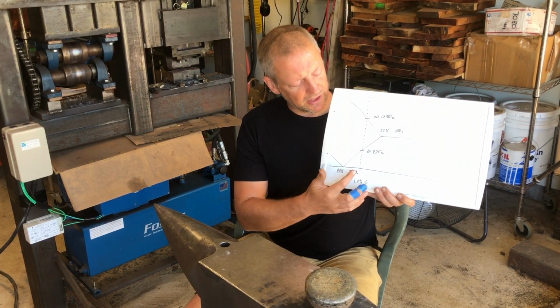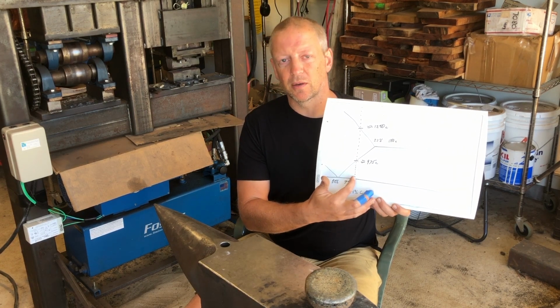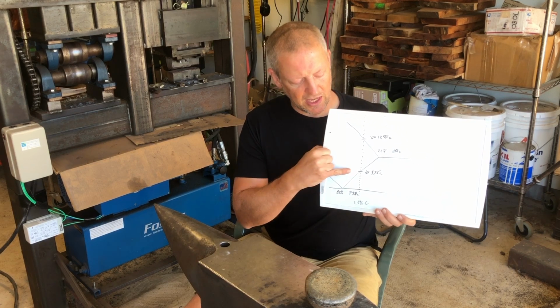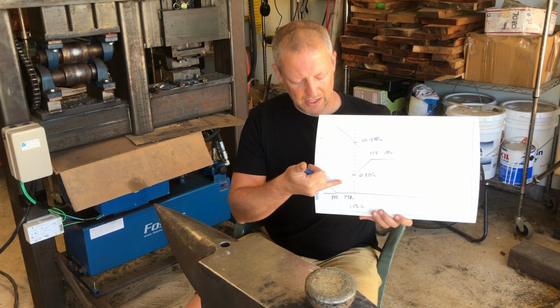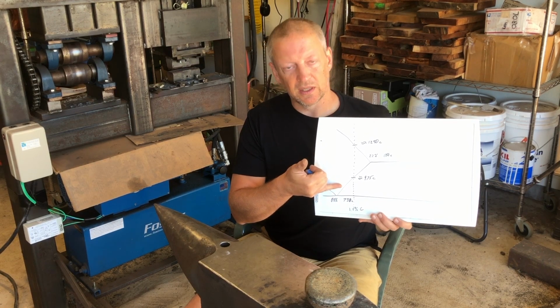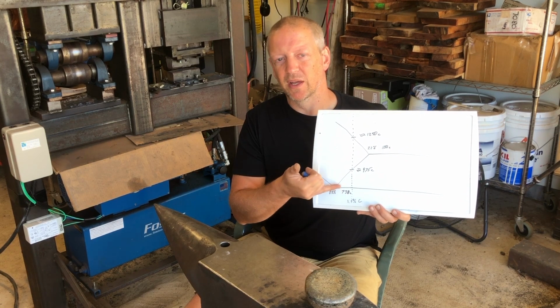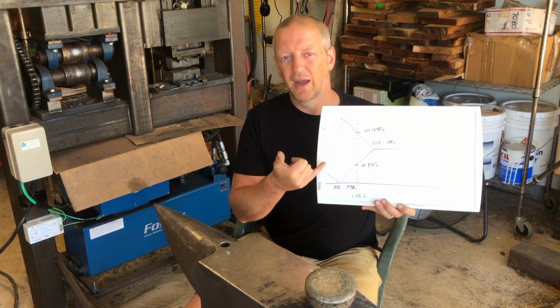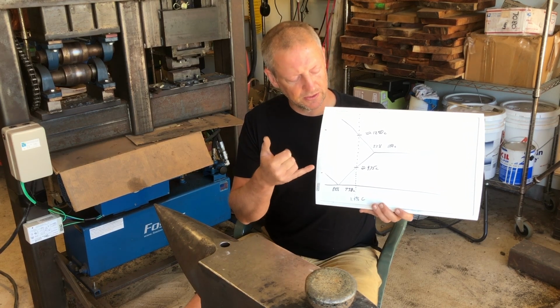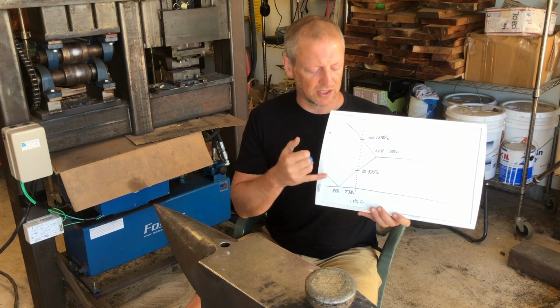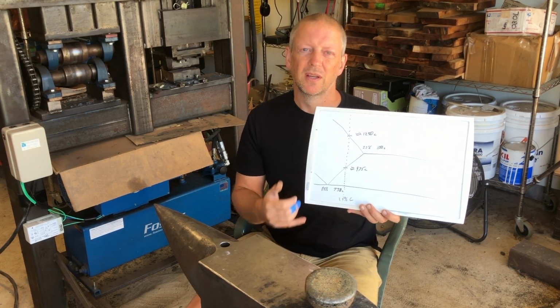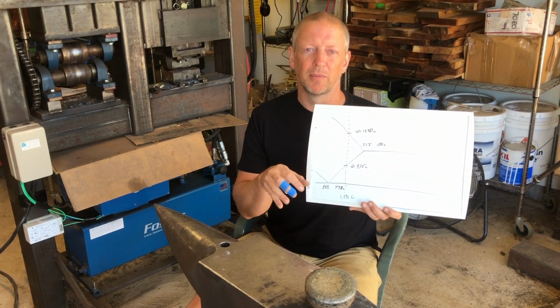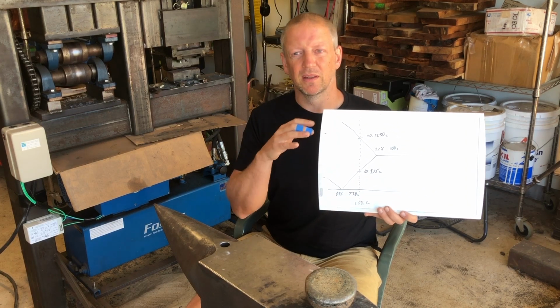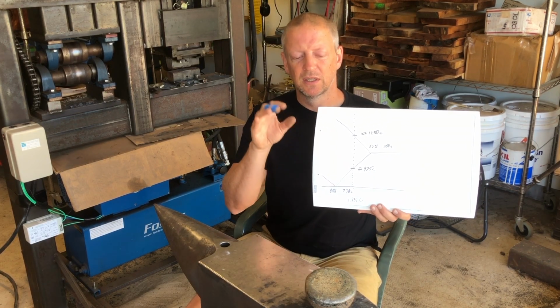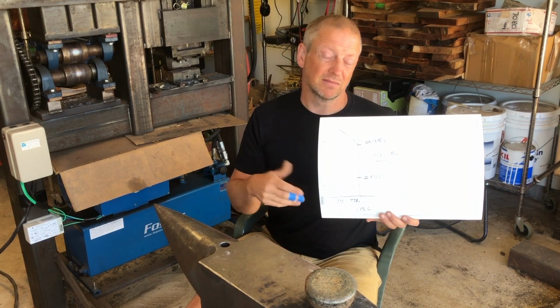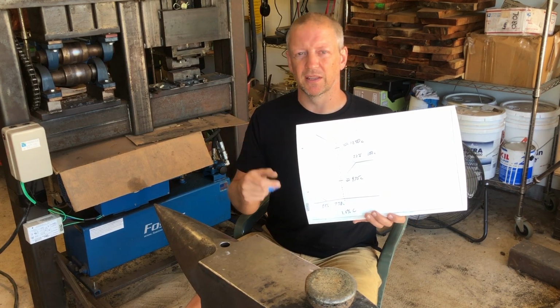But if I have a 1.5% carbon steel, and I have not reached the ACM line, I can essentially draw a line over to the ACM line. And where I am on the ACM line is going to tell me how much carbon is in solution, how much carbon is still as carbide. So it's a really handy thing to know, and you can keep it in mind when you are choosing your forging temperatures, because that will tell you about how much carbide you have present. My finding has been that too much carbide in the steel during forging clearly makes it harder to forge and makes it more likely to fracture.